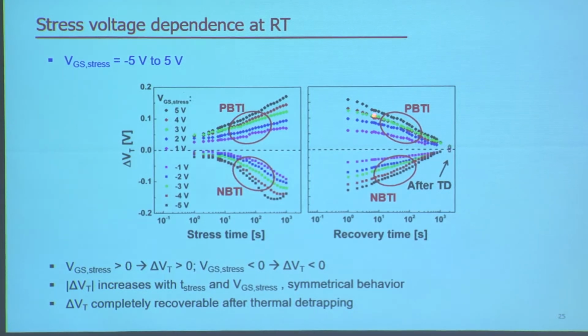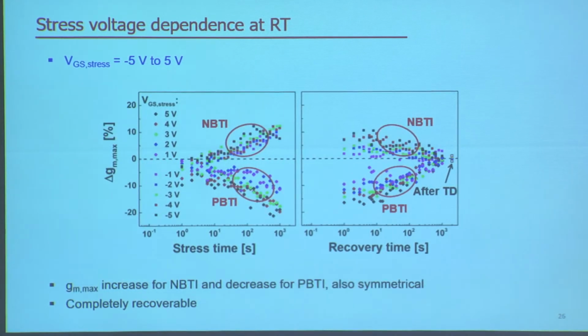After recovery, and especially after final thermal detrapping, we see that the delta VT shifts are completely recovered for all 10 stress voltages. Next, let's look at maximum transconductance, delta GM max. And we again see a symmetrical behavior. But the difference in this picture compared with the earlier one is that for NBTI, we actually see a temporary boost of GM max. And for PBTI, there's a degradation of GM max. And after recovery and final thermal detrapping, the GM change is completely recovered.